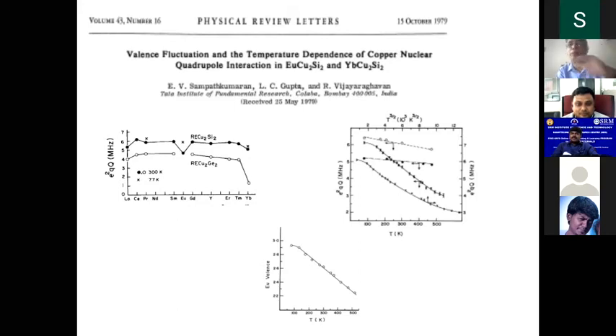You look at the copper element, do copper NMR, and then try to study the electric field gradient at that site, which is plotted here as a function of rare earth. You can see here, if the rare earth valence is 3+, in these two families, silicon and germanium, the valence is stable, and the electric field gradient value should be about this much. When it is fluctuating, intermediate, you can see the value is dipping here.